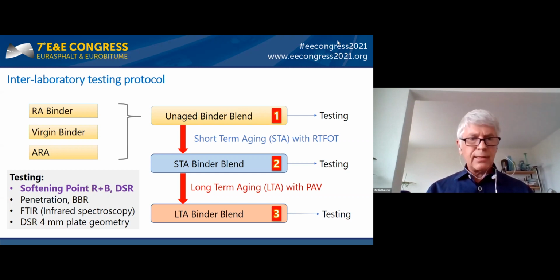However, penetration is still a value which is well known, especially among practitioners. And that's why we also included the penetration tests for a few labs. And we also needed a way to look at the low temperature properties, which we were doing with a bending beam rheometer equipment. But this is also using a lot of material, even though it's only made once at the end of the long and short-term aging. So a few labs did also perform this BBR testing.